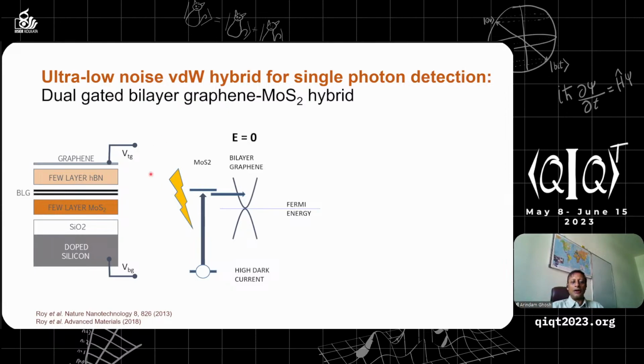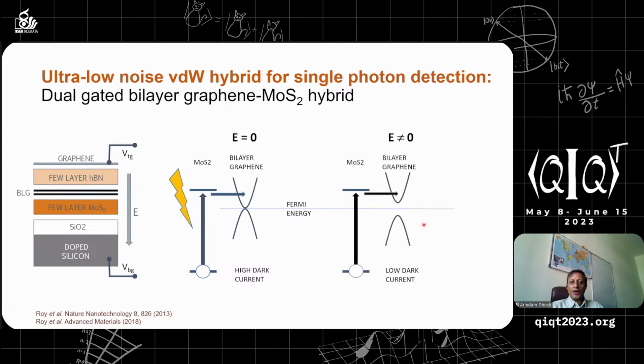So what we did now, exactly the same as the quantum computing guys were trying to make qubits with graphene electrodes, we applied an electric field across the bilayer graphene between the top gate and the back gate voltage, where the upper gate is graphene and the lower gate is the doped silicon, and that opened a band gap. Now, because of the band gap, I can still transfer electrons from the molybdenum disulfide layer, but the current becomes very small.